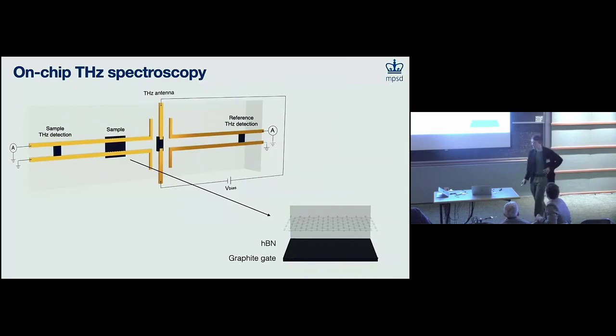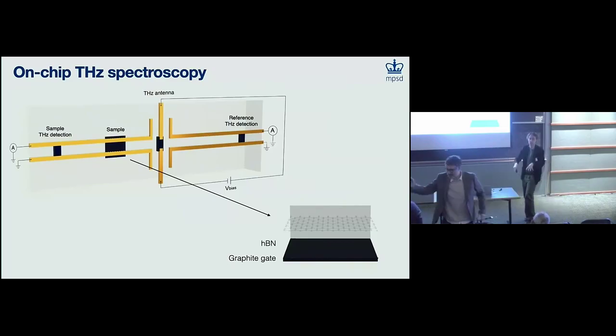The reason we don't print the waveguides first is because if you have these waveguides that are 300 nanometers thick, and then you put a 2D material on top, it's going to be like the Grand Canyon. This is going to fall in. Also, the top of these waveguides, 300 nanometers of metal, is very rough, so it's not ideal. It's definitely more labor intensive to do it the way we do it, but I'm convinced it's the best way. You build the heterostructure first, then you build the circuitry on top every single time, made to order.